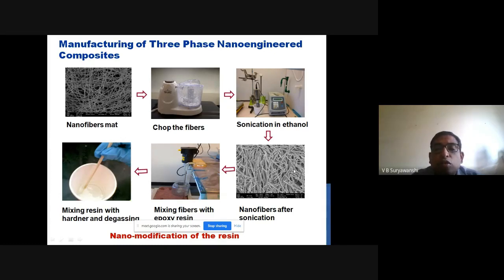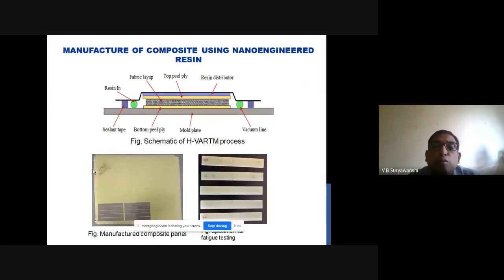What will happen? Nanofibers are strong. The glass material is strong. It will improve the properties of the resin. Polymer generally is weak among the fiber and resin. And by adding the small nano size fibers to the polymer, we are improving the properties of the resin. Now that improved resin is used in the polymer fiber reinforced composite. So what we do, the fabric is laid up here, fabric layup, and this modified resin is given as the input, and it will mix with this fabric and we get a composite like this. So this is called the composite using the nano engineered resin.